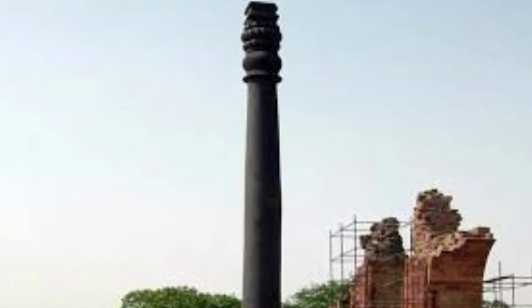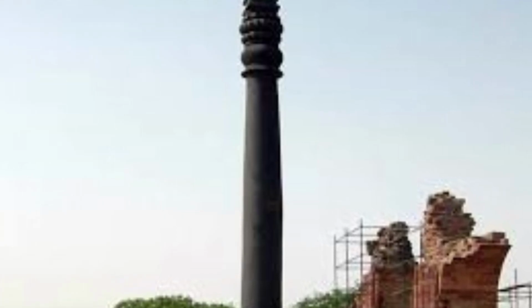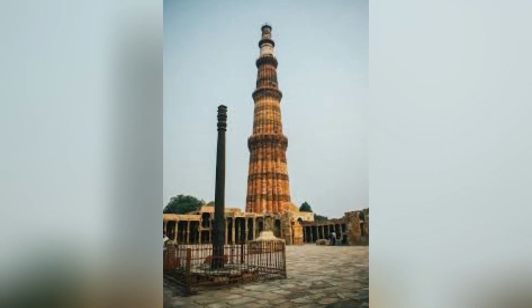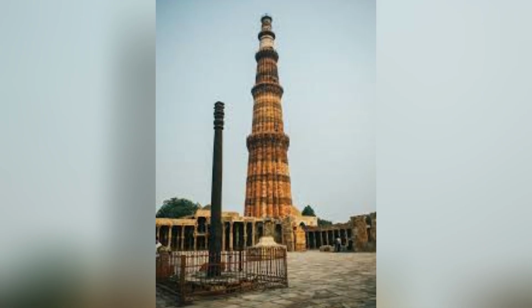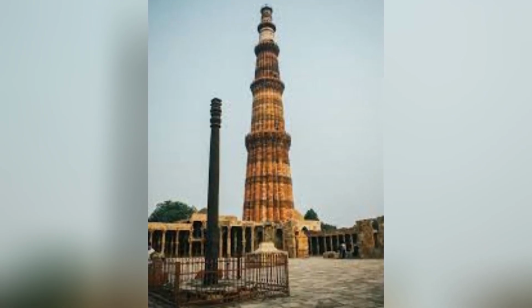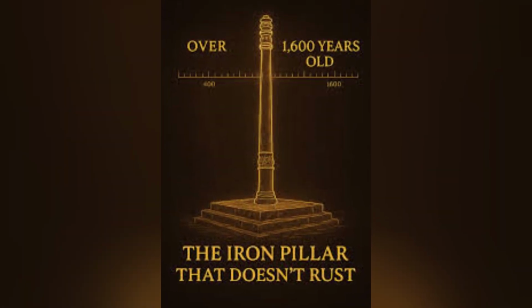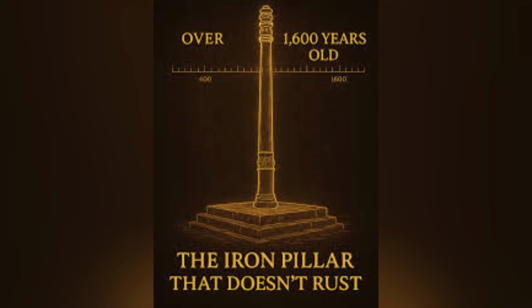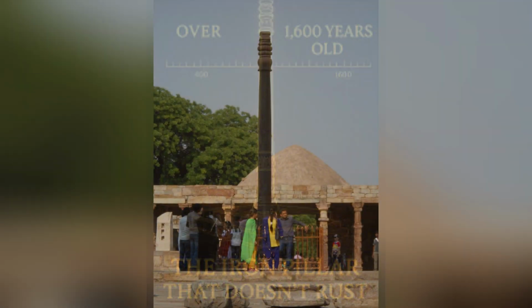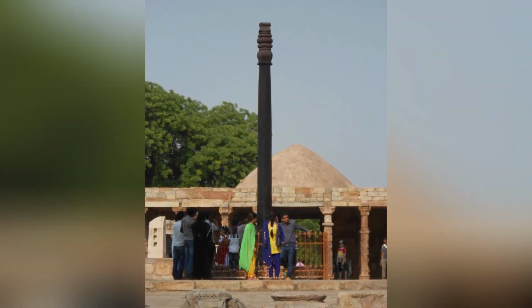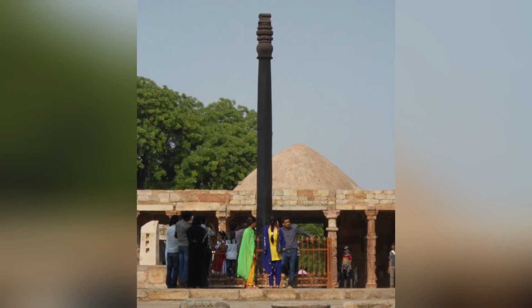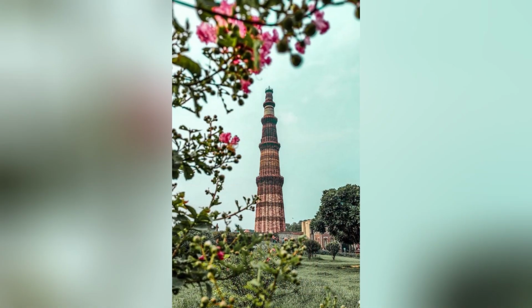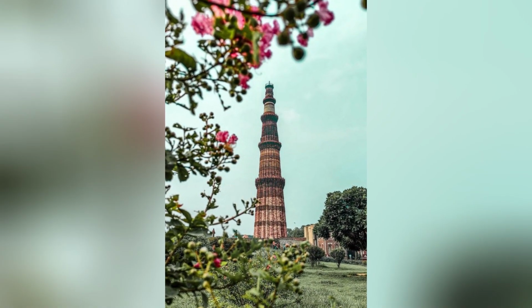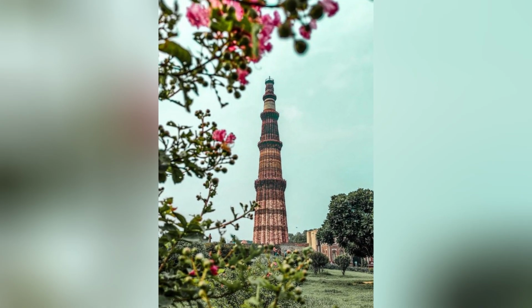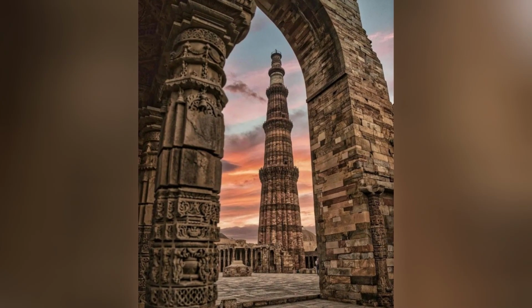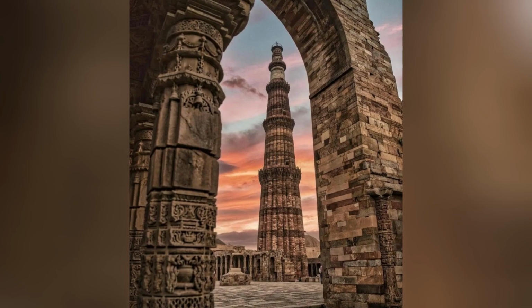The question of whether the specific laterite deposits that were used to produce the iron of the Delhi pillar can be identified is one that has been pursued through the comparison of the trace element composition of the pillar's iron with the trace element compositions of laterite ores from different regions. The trace element fingerprint of the iron, which includes the concentrations of phosphorus, silicon, manganese, copper, nickel, and other elements, can potentially be matched to the trace element fingerprint of a specific ore source, providing information about the geographical origin of the raw material. The analysis conducted to date has suggested that the ore came from the laterite deposits of the Vindhyan region of central India, which is consistent with the historical evidence that places the original location of the pillar in the Udayagiri Vidisha region of Madhya Pradesh.